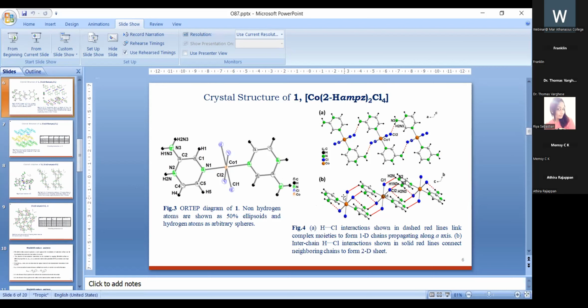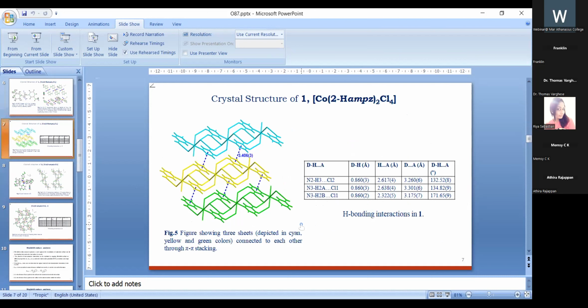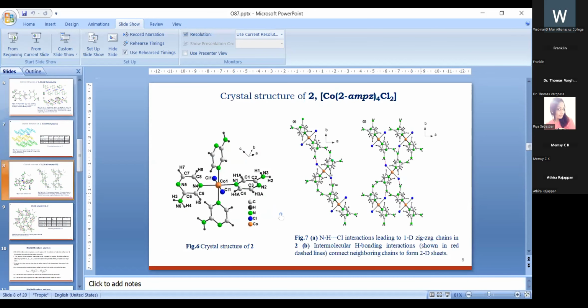Crystal packing in 1 is stabilized by hydrogen bonding interactions, leading to one-dimensional chains, which are further connected to form two-dimensional sheets, as shown in figure 4A and B. Apart from hydrogen bonding interactions, pi-pi interactions also stabilize the crystal structure. In the crystal structure of 2, Co2+ is at the center of the octahedron, surrounded by 4 2-aminopyrazine moieties and 2 chloride ligands.